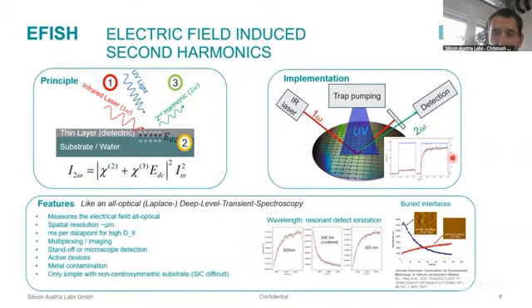When you do transient measurements and not just a quick interrogation after the traps are populated, when you make transient measurements like these here below, there are three examples here for different wavelengths, then you get such multi-exponential curves. And there you see the dynamics, the balance of the pumping of the traps and the decay of the traps. And this is very similar in terms of interpretation to what is known as deep-level transient spectroscopy, or the slow version, which is called Laplace deep-level transient spectroscopy, where you look at these multi-exponential decays or rises. But this DLTS is a contact measurement, so it doesn't have spatial resolution like an optical interrogation. And you need a contact, and you even need an active device for this. And for eFish, you do not need all this.